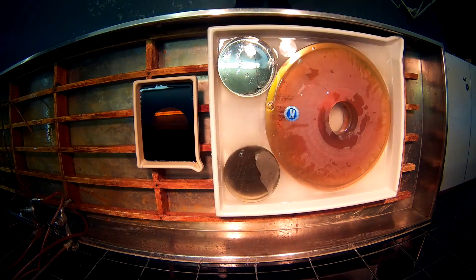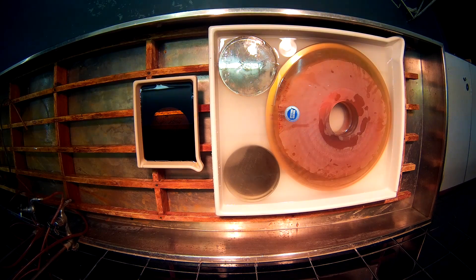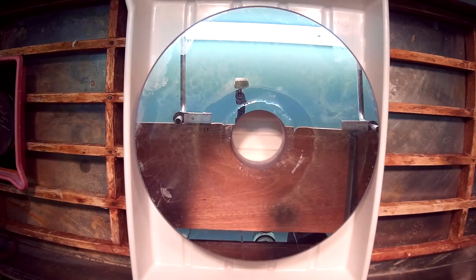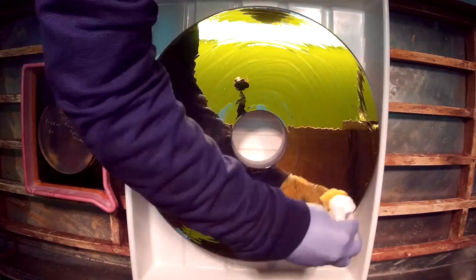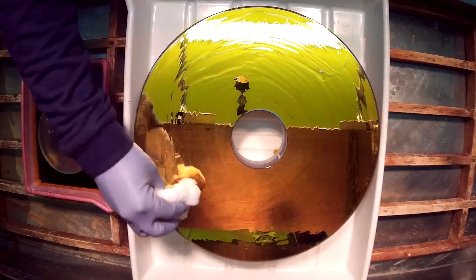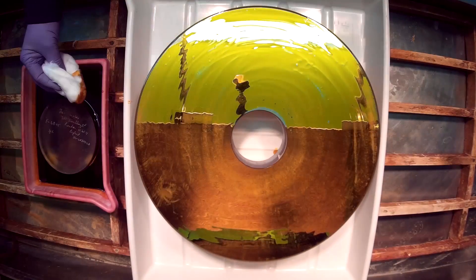Ferric chloride is brown in color and it attacks all metals. Since the large mirror had an aluminum ring attached to it, it was soaked face down in potassium hydroxide overnight. However, the coating would not budge, but at least the metal ring came undone, so it could be stripped using ferric chloride, as can be seen in this time lapse. It took about 3 hours to completely clear.